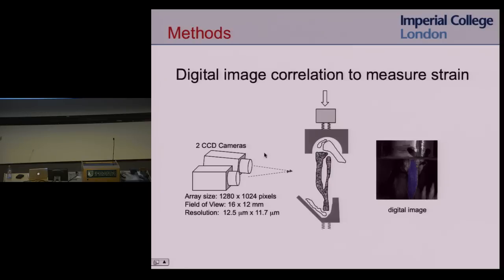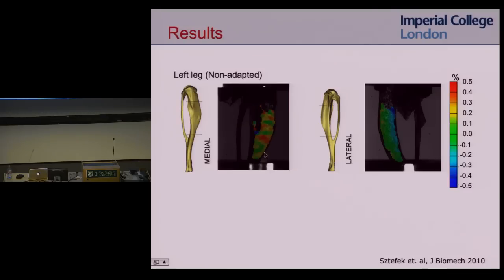So we use digital image correlation to measure strain. Basically, you speckle the bone. We do that by painting it white and then spray painting it to get a speckle pattern. Then you load it. So these are in dead mice, just the legs of the mice. You load it just like you would in a live mouse, and you watch the speckles with two cameras. And so then you can trace how the speckles move and get a strain pattern over the entire surface of the bone. So instead of just having two strain measurements from strain gauges, you have the entire surface of the bone. So this is what the strain looks like.